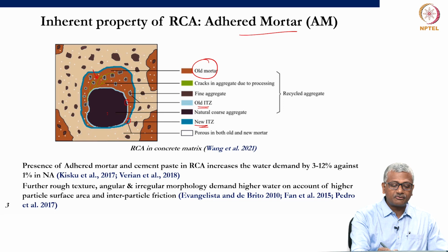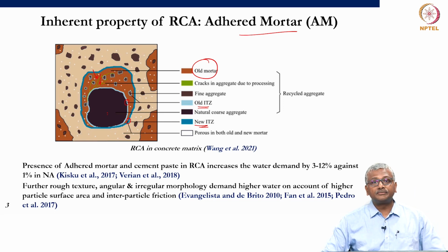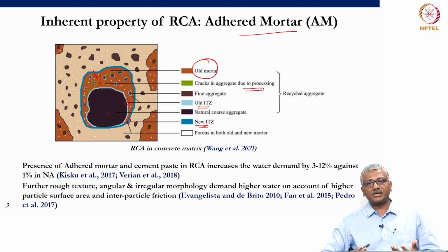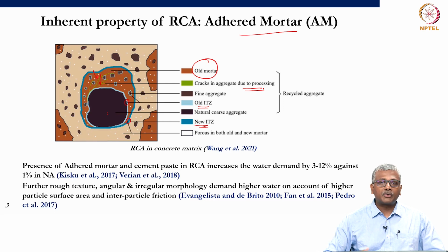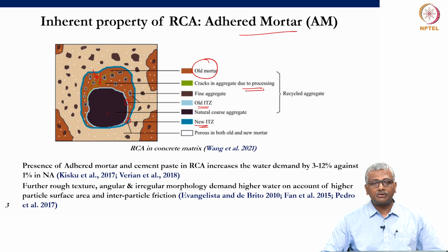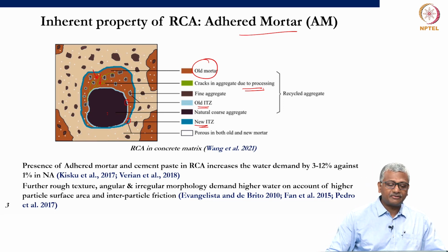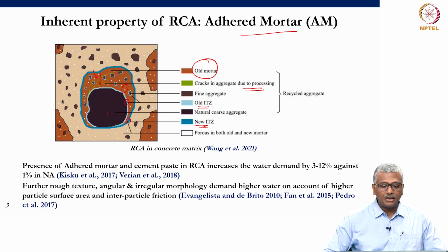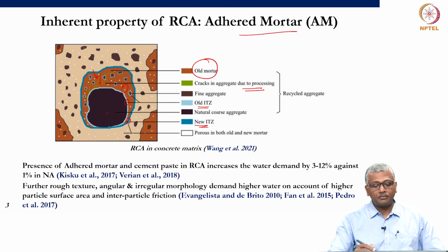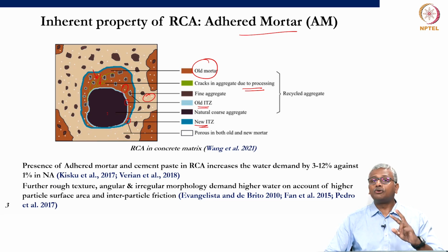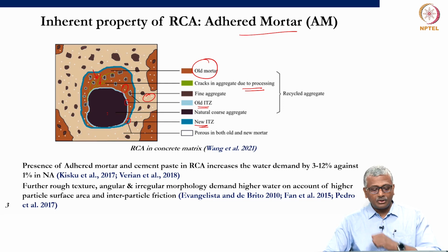And then you have these cracks and fissures that have come into the structure of the recycled concrete aggregate because of processing, because we are crushing it, we are heating it, and so on and so forth. All the processing will lead to some sort of damage to the aggregate. So, those are cracks that have been introduced due to processing, and definitely there are pores and voids in the older adhered mortar, and pores and voids also in the new concrete. So, your system now becomes a lot more complicated, as was discussed in one of the previous lectures. Now you have two ITZs, right? Two interfacial transition zones. One is the old one and one is the new one.